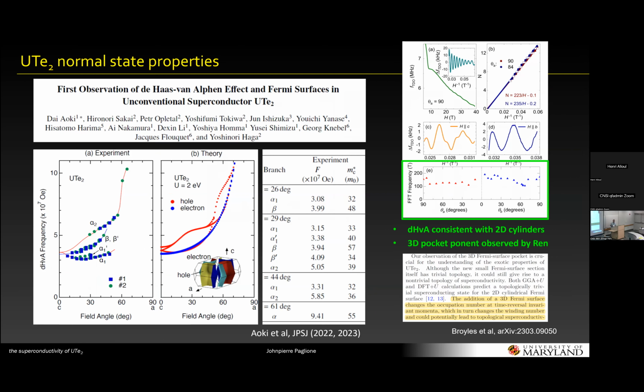So these masses are then F electron masses, or are they from the D's? No, they have to be F's, right? Yeah. So that's what I'm saying, that this band structure is composed of these P and D sheets, and the quantum oscillations measurements confirm that, but yet they're very heavy. But you don't have F bands at the Fermi surface. You have to. But you showed the band structure and you said that it's only the P and D bands and there's no F bands. Where are the F bands?